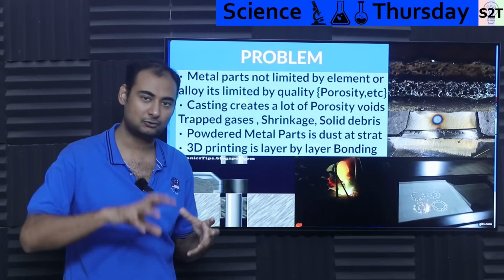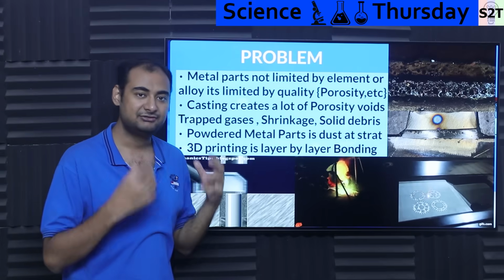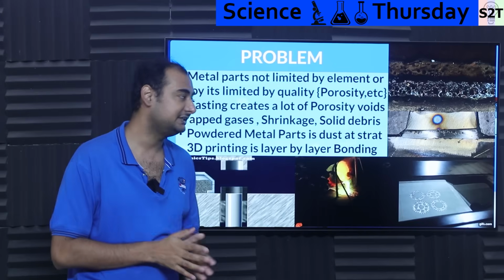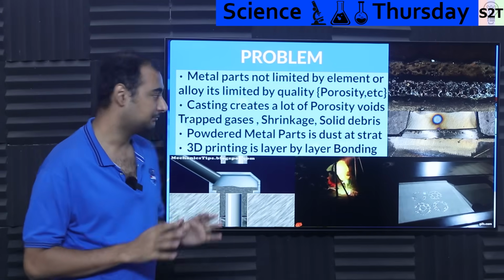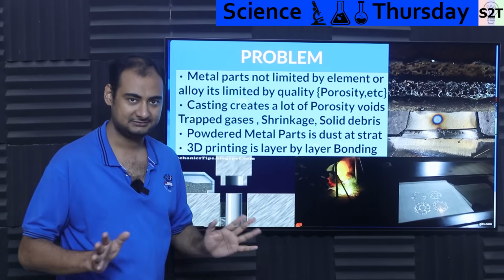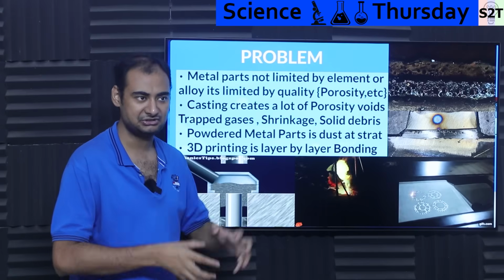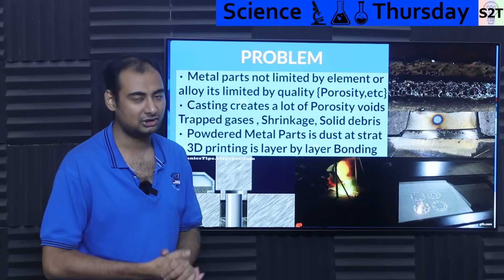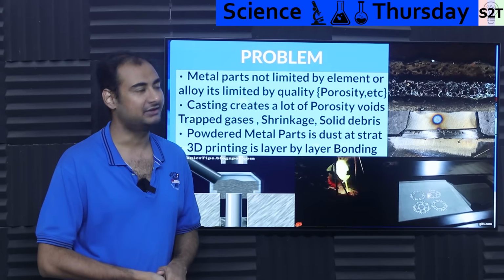And the same happens when you are forging, casting, things of that nature. If you have too much void or too much porosity, it's bad. Let that be very clear. Porosity is just bad. You do not want voids inside your material. You want one absolutely solid part. But it turns out it's very difficult to achieve.